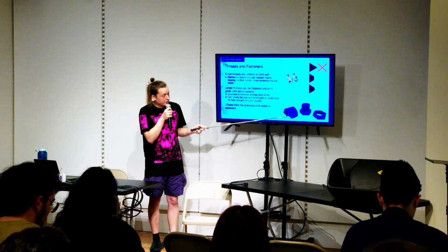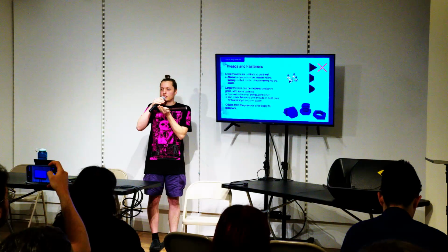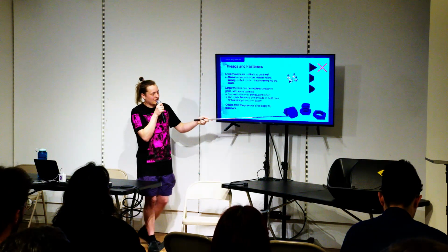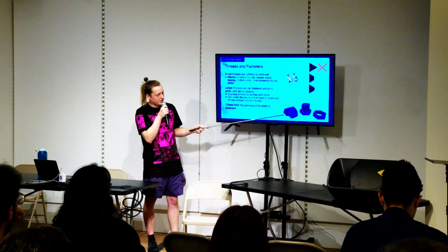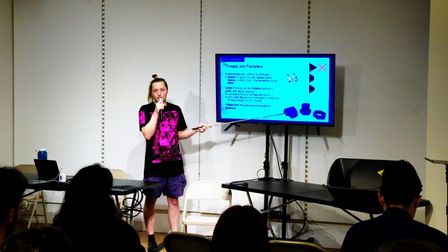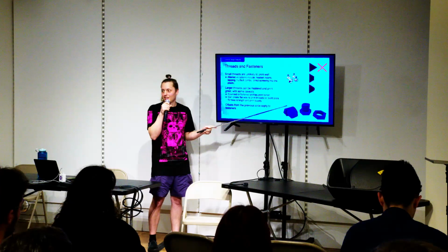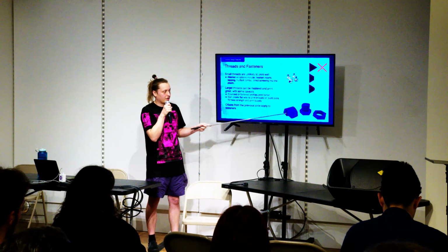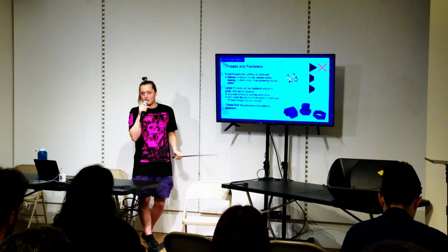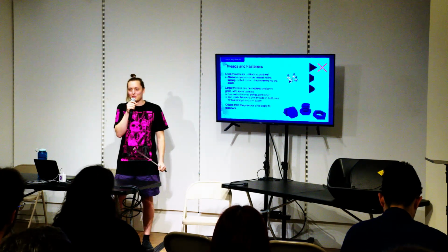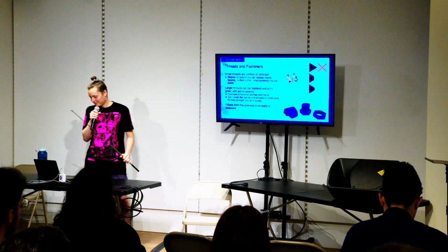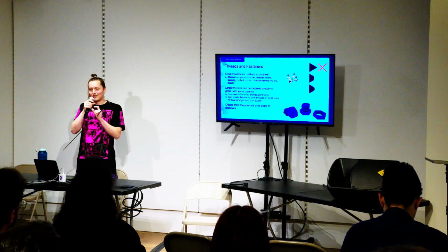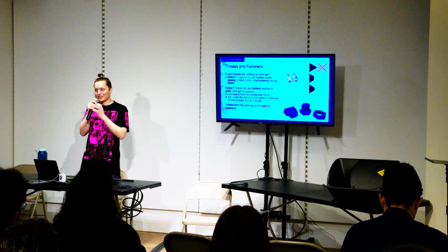And then one thing that you can do, due to the layer lines being the highest rate of failure for prints, instead of printing them upright, you can actually just slice a side off of the bolt and lay it flat on your build plate. And then you gain the print strength from the layer lines going through circularly through the orientation of the print. And it functions exactly the same, and you gain way more strength that way. And then again, pay attention to your offsets. If you don't add any offset, the two parts are not going to mate at all.